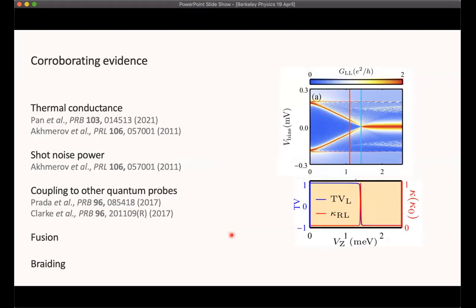Now, this is beyond the time I have for today, but there are several other things that you can do to corroborate this evidence that you've entered this topological superconducting phase with your system. There is an expectation that at the topological phase transition, there should be a peak in thermal conductance. So superconductors don't typically demonstrate thermal conductance, but at this phase transition, this red line here, prediction shows you that not only should thermal conductance peak, but it should be quantized.